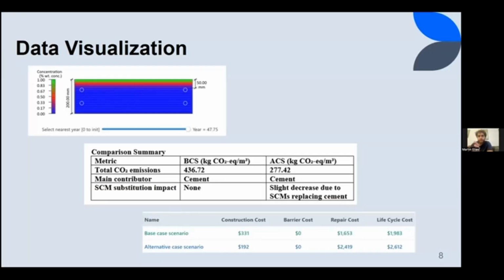And finally, the data visualization appears as different figures and graphs having different parameters. The first figure shows a section of a slab designed using our ACS mix, showing a simulation of chloride ions penetrating into the slab, which remains near the surface, so relatively low, over a period of 47.5 years, indicating high resistance to chloride penetration, especially since our mix is considered to be in a marine environment.